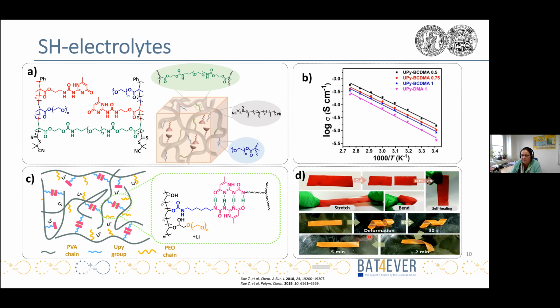The temporary shape can be achieved due to the interaction of the PVA with the polyethylene glycol side chains, whereas the supramolecular network gives the possibility for the permanent shape of the film and the mechanical integrity.